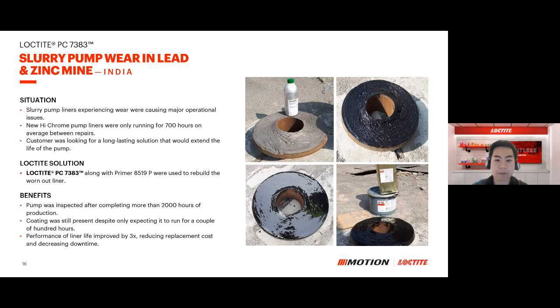We then used our Loctite PC7383 along with our metal primer to rebuild the worn-out areas of the liner. The pump was then inspected during their next major shutdown after 2,000 hours of production, and the coating was still present at that time, even though it was only expected to last for a couple hundred hours. The performance of the liner was improved by almost 3 times, reducing replacement costs, providing major cost savings for the customer, and also decreasing their downtime.